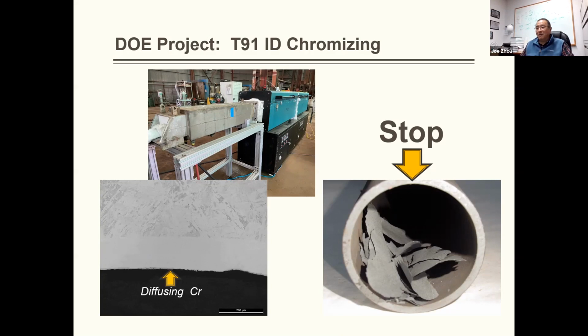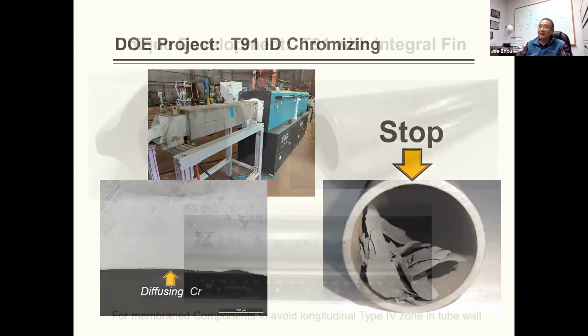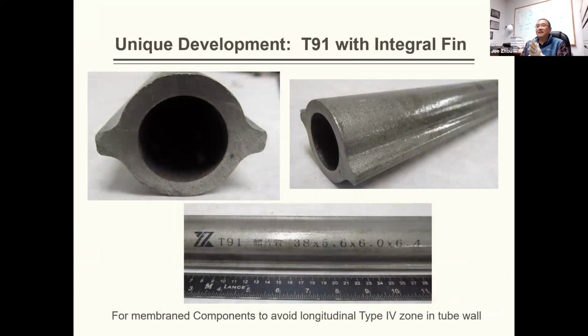So we are developing this program: by diffusion of chrome from the tube ID surface, we create a thin chrome-rich layer, and then we can stop the steam scale formation. So this is one case we are still working on. The other case is CES has been working with one of the Chinese steel mills, developing this unique T91 integral fin tubing. When power generation efficiency goes up, pressure and temperature go up, so more and more 91 will be used in building membrane panels, like in a lot of CFB units now, even in the superheater.